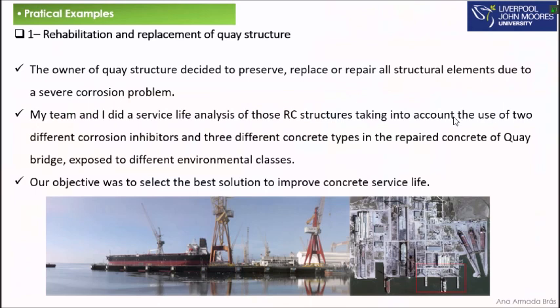So a massive refurbishment and a massive rehabilitation activity occurred 20 years ago, and after 20 years, all the concrete was corroded, which means that this was a major issue in terms of service life. So my team and I did a service life analysis of those reinforced concrete structures, taking into account the use of 2 different corrosion inhibitors and 3 different concrete types.